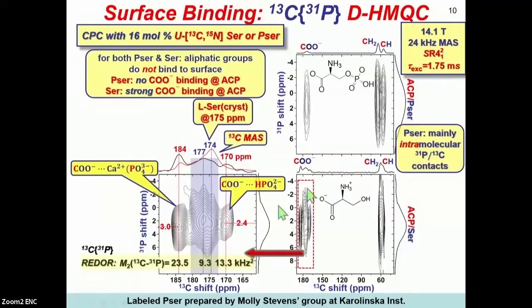For serine, on the other hand, we do see a strong binding at the carboxy site with the ACP surface. And here you see a zoom of the carboxy region. We can identify three groups of peaks, which have quite different dipolar second moments, carbon-13 phosphorus. They are very different among the groups as well. These were obtained from carbon-phosphorus REDOR NMR.